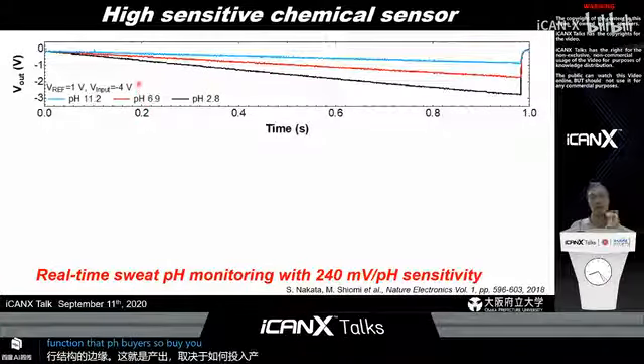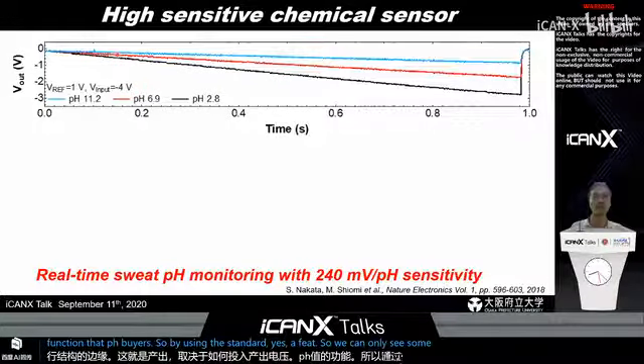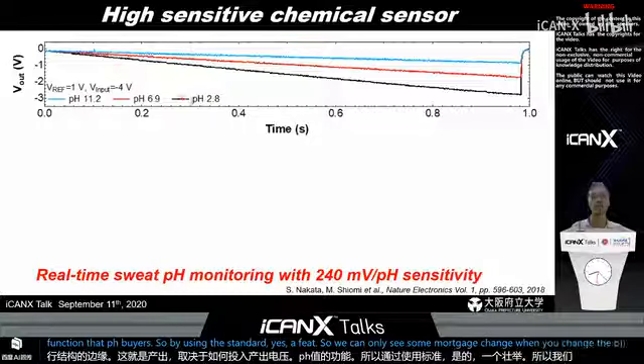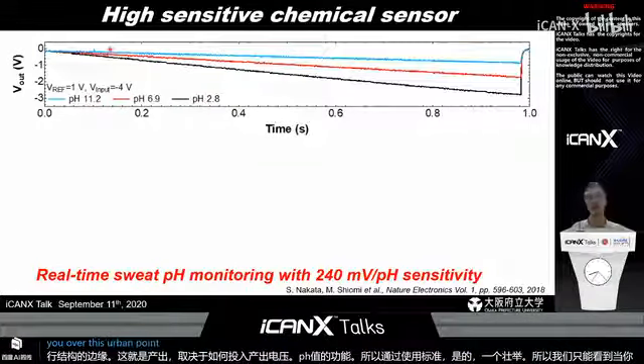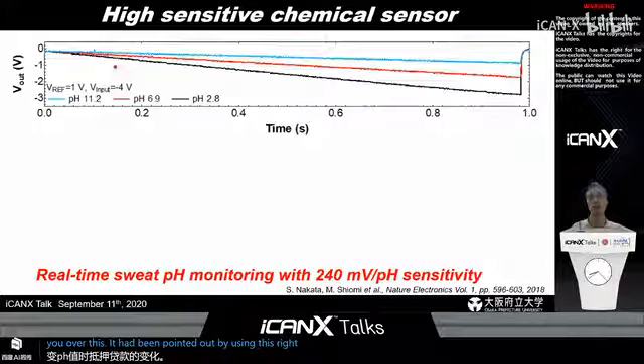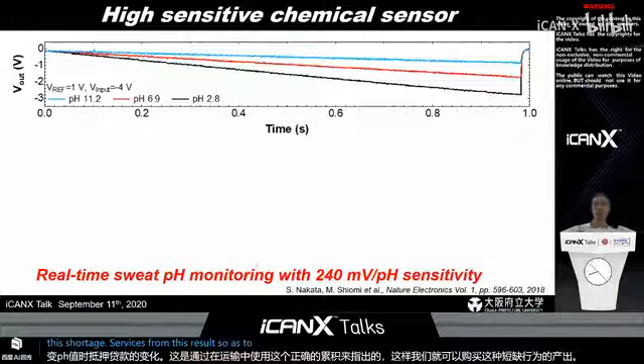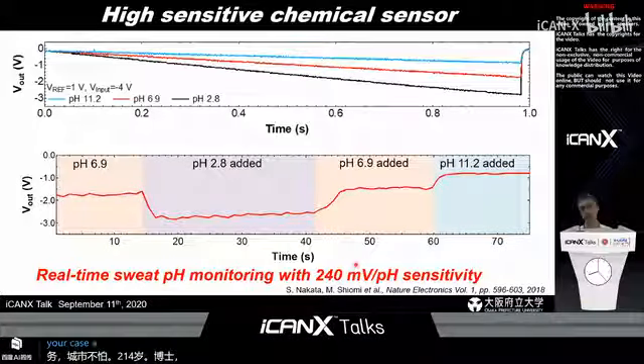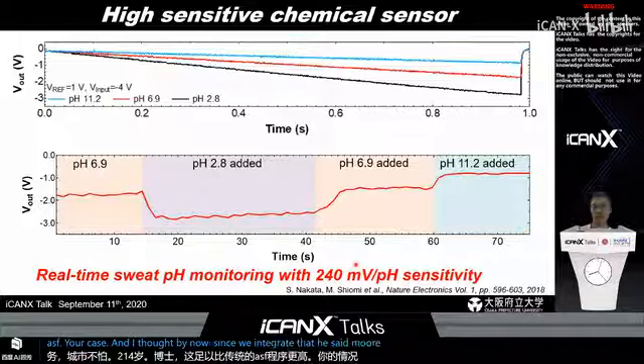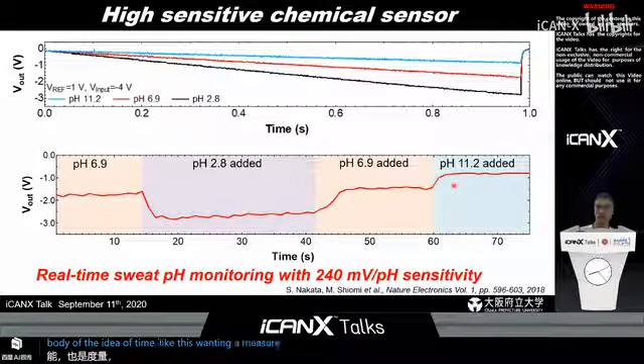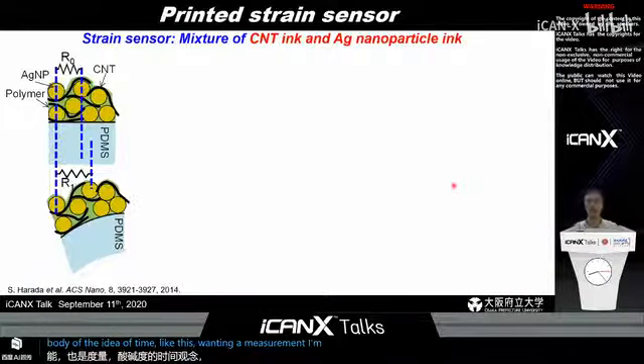By using the standard ISFET, we can only see this voltage change when you change the pH value from 2.8 to 11.2. However, by using this accumulation and transfer technique, we can amplify the output behavior like this. From these results, the sensitivity is roughly 240 millivolts per pH, which is roughly 4 times higher than conventional ISFETs. And since we integrate the reset function, we can also measure the pH value in real time, like this continuous measurement. So that is a chemical sensor.